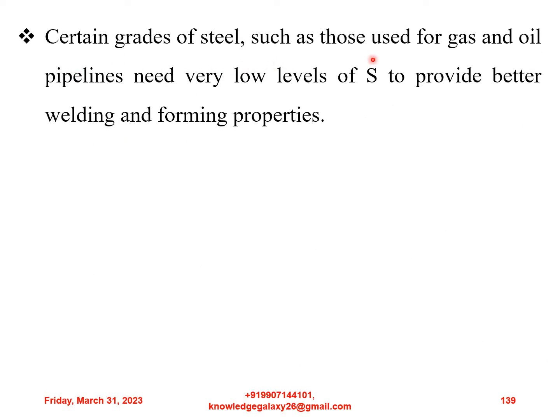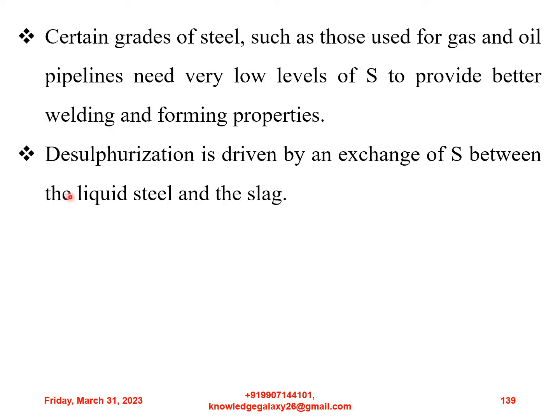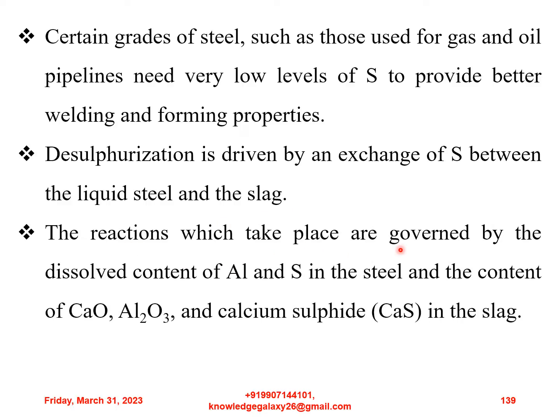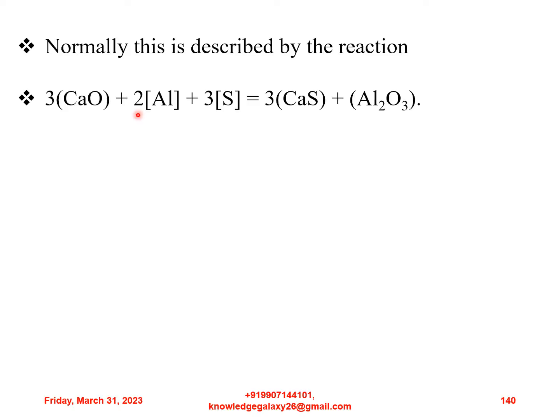Certain grades of steel, such as those used for gas and oil pipelines, need very low levels of sulfur to provide better welding and forming properties. Desulfurization is driven by an exchange of sulfur between the liquid steel and the slag. The reactions which take place are governed by the dissolved content of aluminium and sulfur in the steel and the content of CaO, Al2O3 and calcium sulfide, that is CaS, in the slag. Normally, this is described by the reaction 3CaO plus 2Al plus 3S gives rise to 3CaS plus Al2O3.